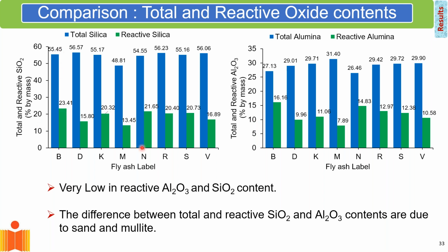Now, if you look at these fly ashes that we collected, the blue bars here represent the total silica. And you can see the total silica is like a healthy number. It's like 50%, around 50% of the total fly ash is total silica. But if you look at the silica that's present in the glassy spheres, it's a much smaller number, less than half of what is indicated by the total silica.